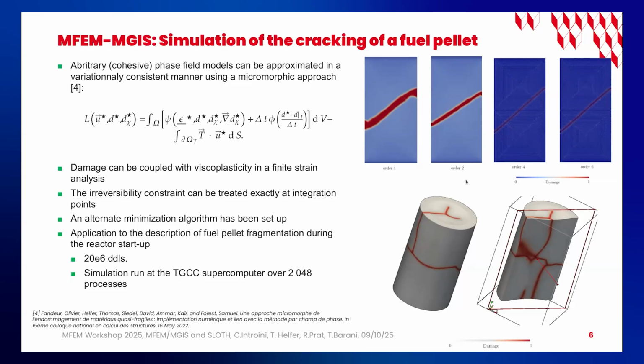And the second example, which is closer to our main concerns, is the brittle fracture of a fuel pellet during a reactor startup. So this is typically a fuel pellet. The radius is about 4 millimeters. And during the reactor startup, we have a very strong temperature gradient inside these pellets. So the center is hotter than the outer parts. The temperature gradient is about 100 Kelvin per millimeter.